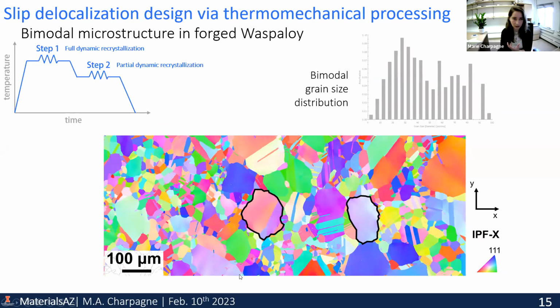meaning that they have some dislocation density. And then we cool down our material to a lower temperature, but continue deforming it so that we have partial dynamic recrystallization, a second round of recrystallization. Because we're at lower temperature, the grain boundary mobility is much lower, so we form smaller grains that don't even have time to consume the first initial big grains. This kind of microstructure is called a necklace microstructure, where you have very large grains that are surrounded by smaller ones. And we end up with this bimodal grain size distribution, as you can see here.